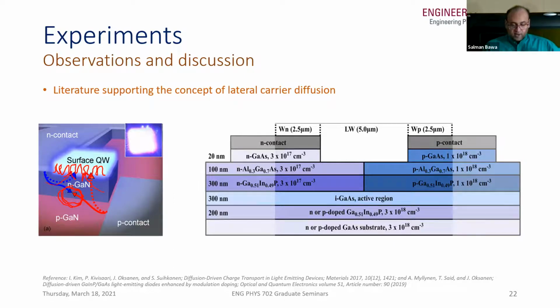The figure on the right uses gallium arsenide and variations of it. And you can see that as the electrons and holes move to the junction, there is some radiative recombination that would happen here, but most of it would diffuse into the intrinsic gallium arsenide region where they would then radiatively recombine, hence calling the intrinsic gallium arsenide here the active region.